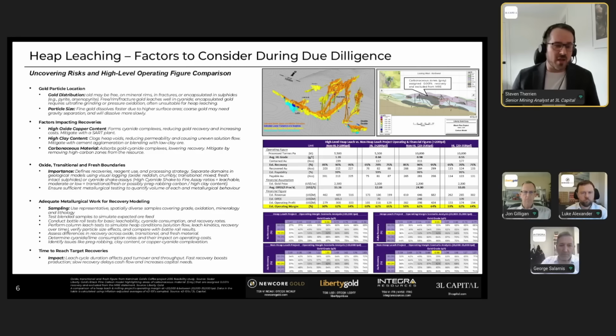the leach pad. I've just got a cross section from Liberty, and you can see they've domained some areas in the deposit that have higher carbonaceous material, and they've applied a 0.001% recovery and excluded any ounces or mineralization in those zones. So they've done a fantastic job at de-risking that aspect of the project and making sure that material doesn't end up on the pad. The other thing that I'll mention, it's really important to know the different domains.